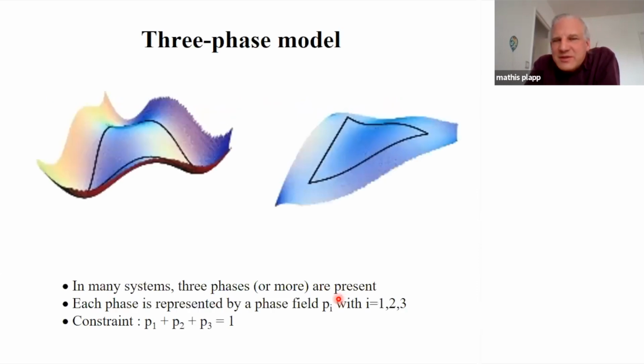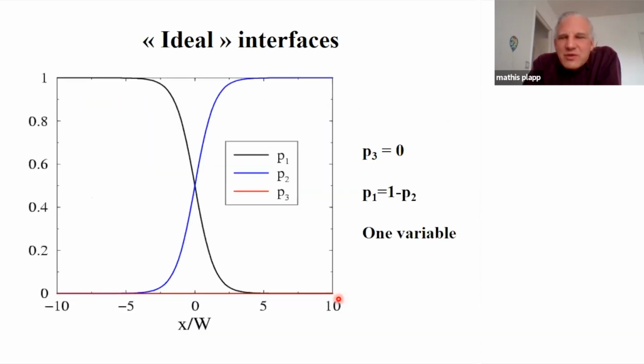Okay, well, I think I have to drastically accelerate if I don't want to go over time a lot. So, the multi-phase field formalism. This is just to say if I have several phases, you need several phase fields. So instead of a double well, if I have 3 phases, I need a triple well. What I need to be careful about is the structure of the interfaces, because if I have 3 phases, I would like the interface between any 2 phases to be clean. That is, there is no adsorption of the 3rd phase.